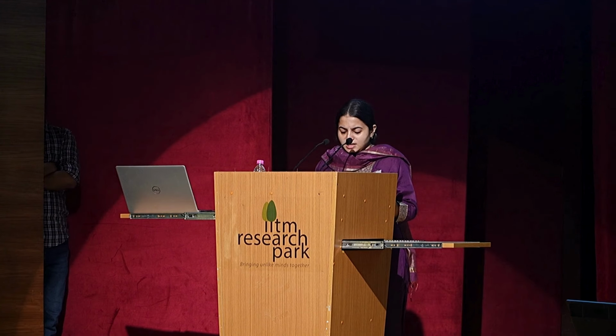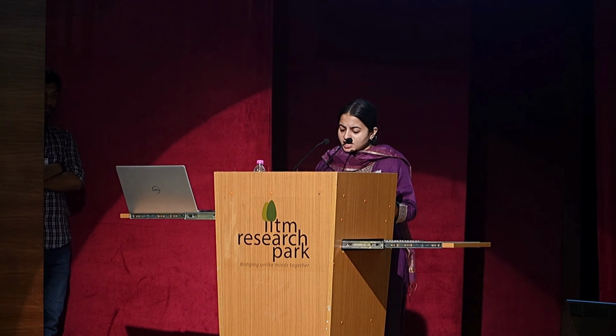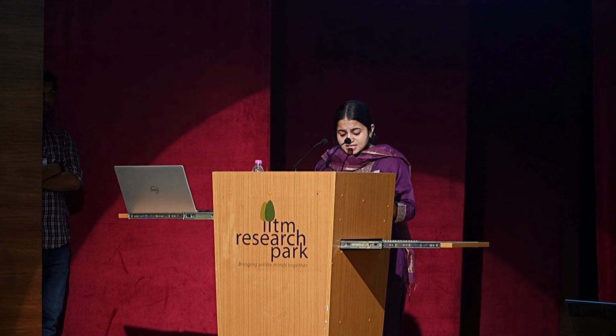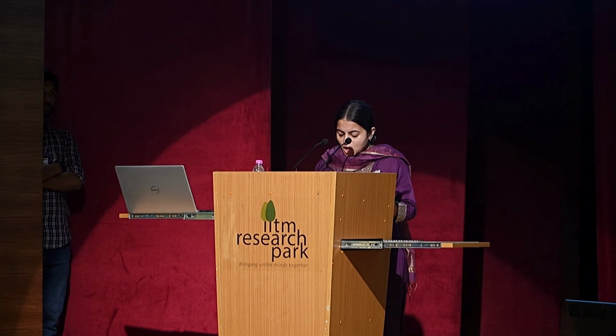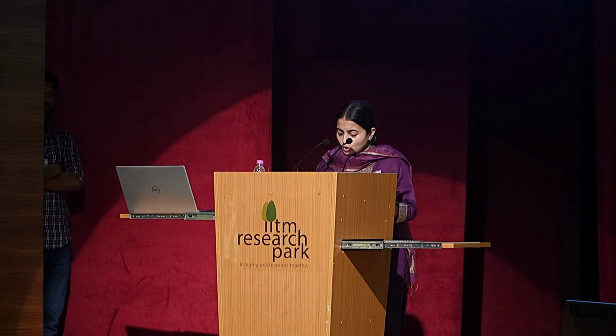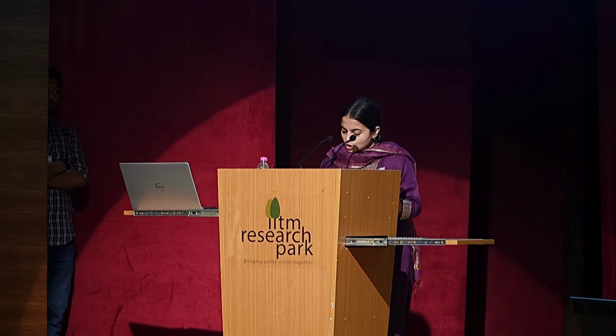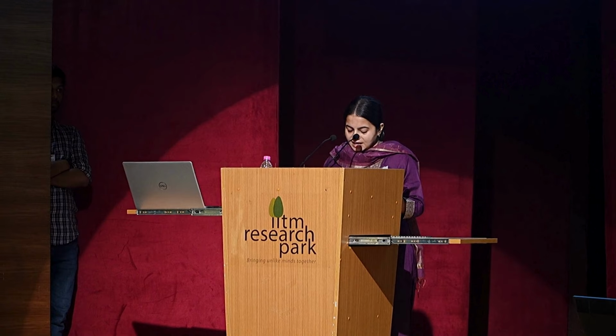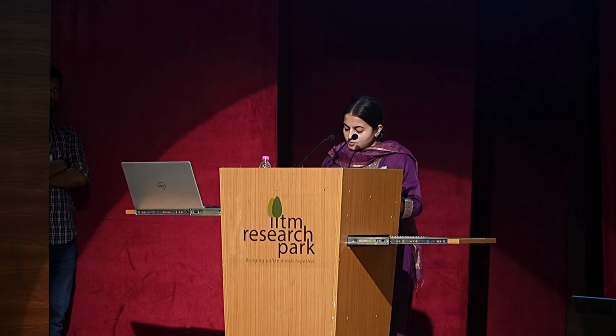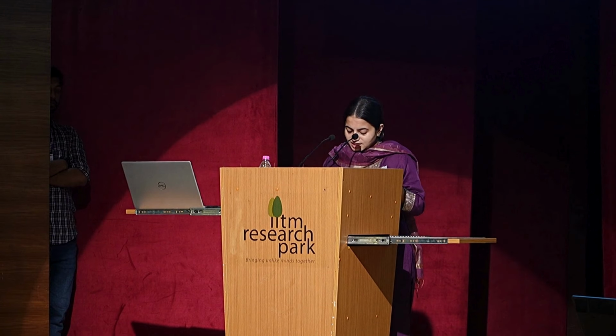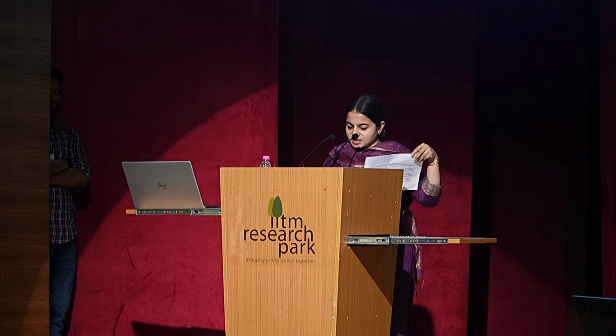In 2023, we published our environmental product declaration, and we reduced our carbon emissions to 592 kilos CO2 per ton of steel. By increasing our RE to 80%, we aim to reduce our CO2 emissions to 200 kilos CO2 per ton of steel, where we are way ahead of the Ministry of Steel 2030 target of 2.2 tons CO2 per ton of steel.